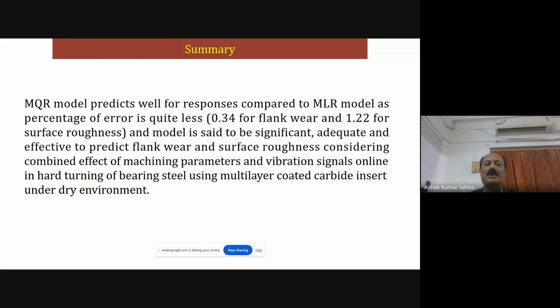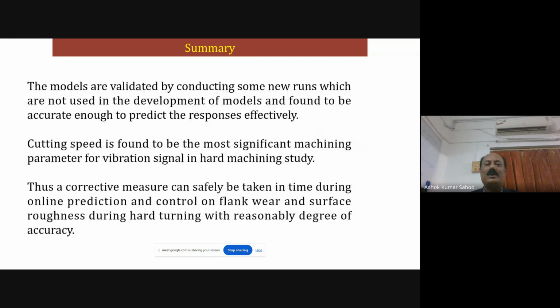MQR model predicts well for the responses for both flank wear and surface roughness, considering the combined effect of machining parameters and vibration signals online in hard turning in dry mode. So the models are validated, cutting speed found to be significant. Thus, a corrective measure can safely be taken in time during online prediction and control of the flank wear and surface roughness during hard machining operation with a reasonable degree of accuracy.